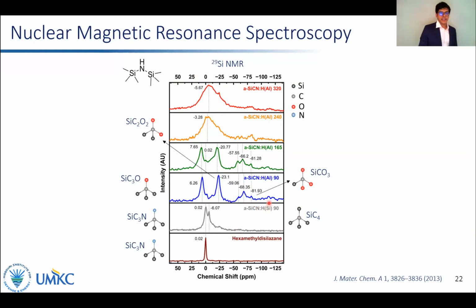Solid state magic angle nuclear magnetic resonance was performed on a select few a-SiCN etched powders deposited at different temperatures. The sample collected from the silicon wafer exhibited 2 resonances: one corresponding to silicon in the hexamethyldisilazane environment, and the other that could correspond to silicon bonded to 4 carbons or to hydrogenated silicon. These peaks are very broad.